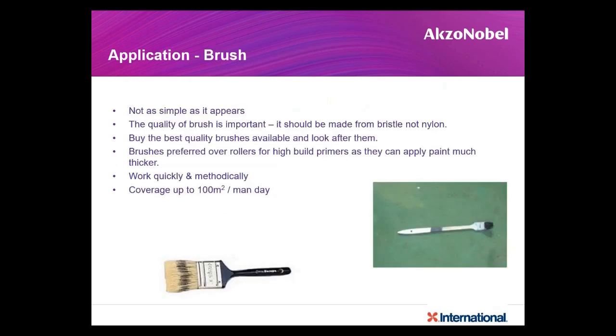Now, application brush, simple. It looks simple, but not as simple. Quality of brush is important. It should be made from bristle, not nylon, because solvent-based paint, you should be very careful. Best quality brushes, I would look after them properly. Brushes are preferred over rollers for high build in order to build thicknesses. It should be worked methodically and quickly. And coverage is around 100 square meters in a man day.